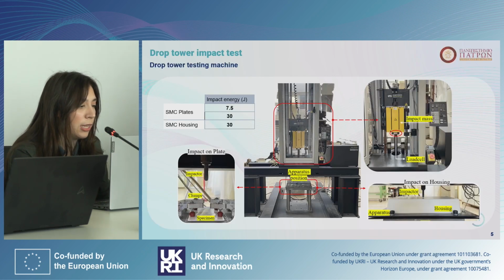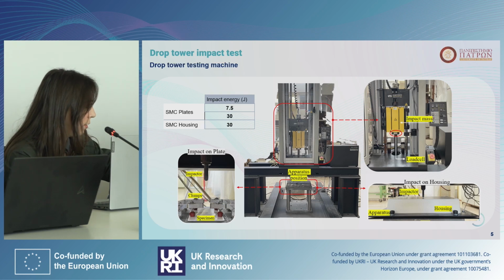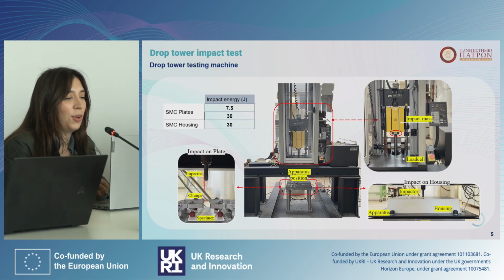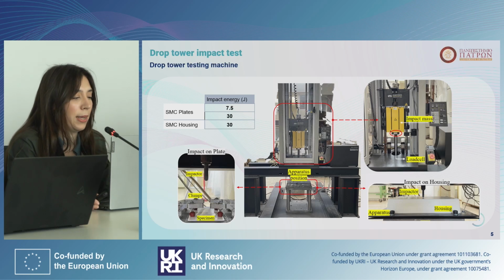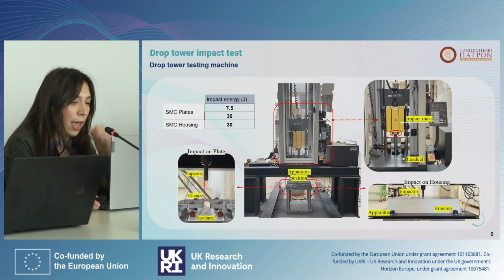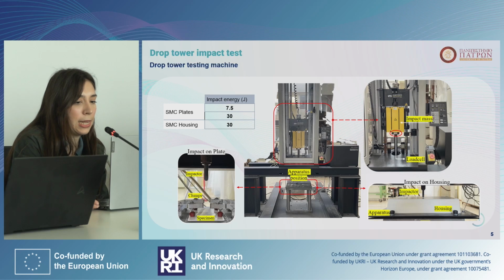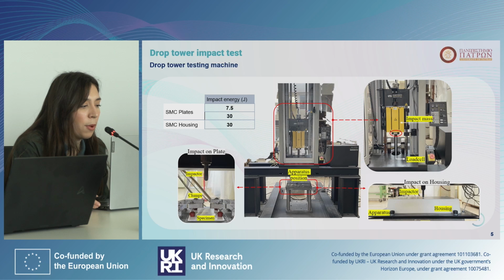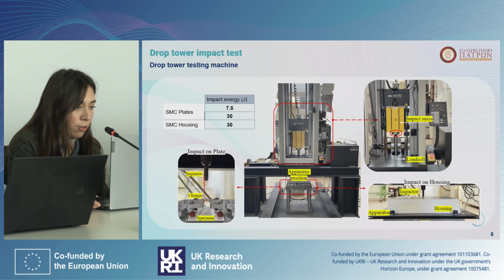So low velocity impact tests were conducted. Low velocity impact tests were conducted using an Instron drop tower machine, and all tests were performed using a 16 millimeter diameter steel impactor with a mass of 6.8 kilograms, while the impact energy was controlled by adjusting the drop height following the principle of energy conservation.